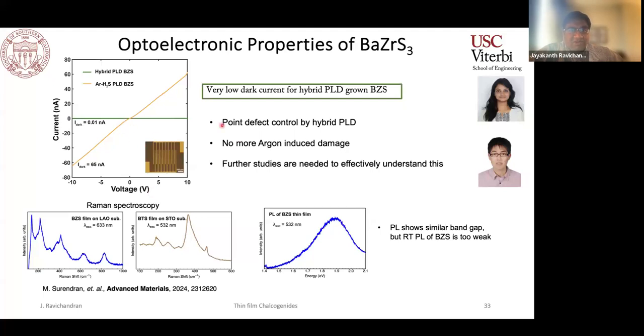One thing that really stood out is that the dark current that we get in our hybrid PLD systems is significantly lower, a couple of orders of magnitude. That suggests that the point defect control, or in general, the defect control is much better in these materials. We also did other routine characterizations such as Raman spectroscopy, PL, and so on.